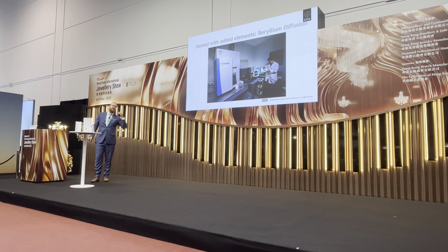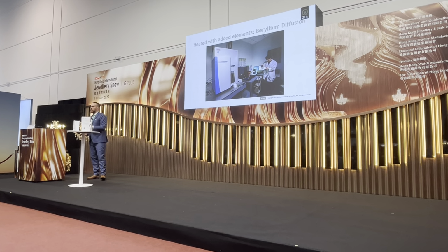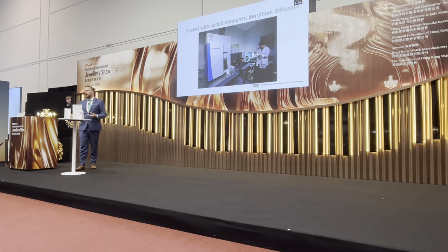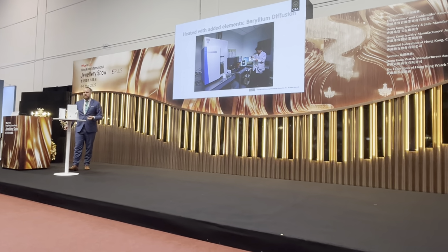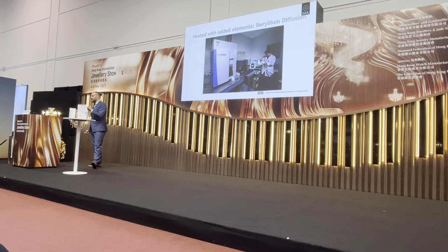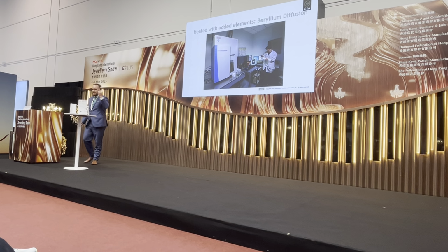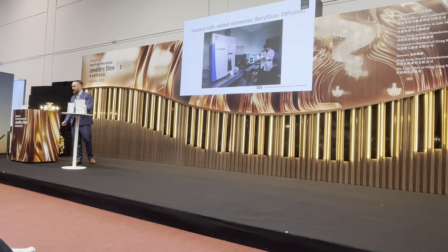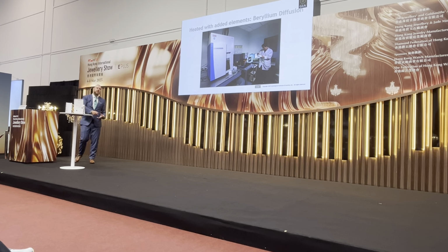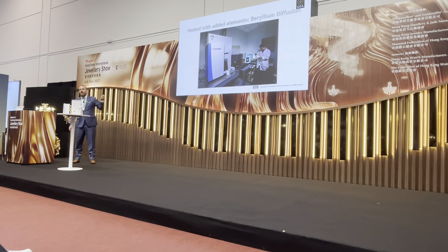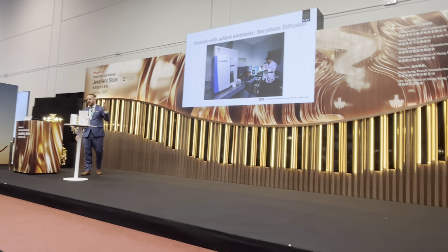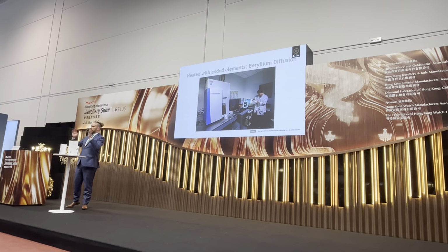So the only way of detecting beryllium diffusion in a ruby or a sapphire is to measure the actual beryllium. There is no indication in the inclusions, in the color zoning, in the FTIR spectra, in the UV-Vis spectra that you can use. The only way that you can detect beryllium in a corundum is by measuring the actual beryllium in the corundum. So at GIA we use an instrument that is called LA-ICP-MS, laser ablation inductively coupled plasma mass spectrometry. That is not going to be on the test.